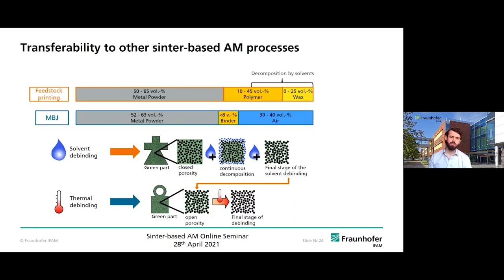And with more binder inside, you need to get this binder out as well to have a residual-free decomposition of it. So some of the materials require a solvent debinding step before the thermal debinding. In some cases, also the closed porosity can be debinded thermally, but it will take a lot of time.